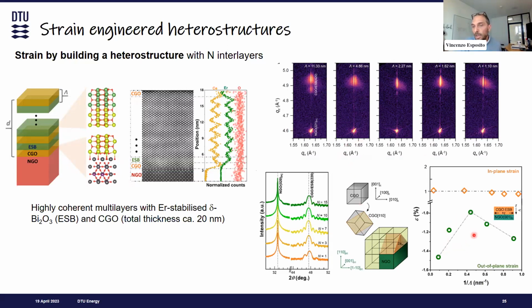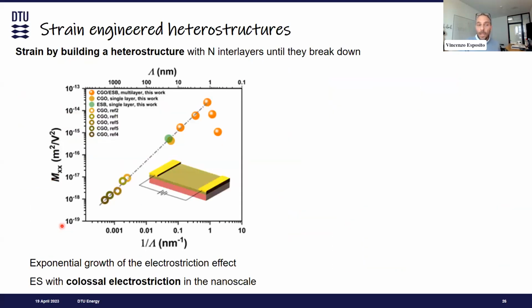And this is the kind of compressive strain that we get in the in-plane direction for this heterostructure, which is made of bismuth oxide, another oxygen-defective fluorite, and gadolinium-doped ceria. So our study case is this heterostructure. This configuration is extremely interesting. What we notice immediately is that depending on the number of interfaces that we put in the system, we can increase electrostriction by orders of magnitude. So in this plot, you see our pristine CGO film, and this is the heterostructure. And you see that it follows a volcano type of behavior, reaching a maximum and then declining.